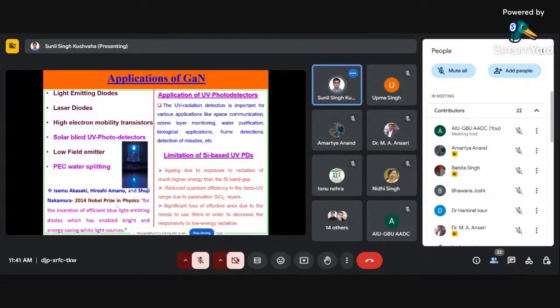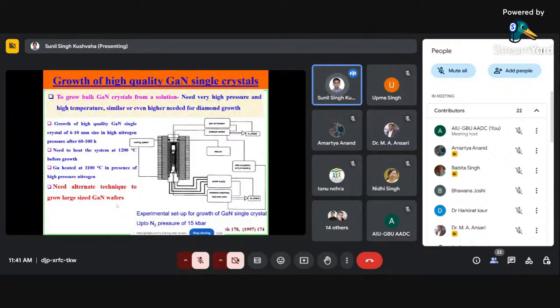As I previously showed, when we put in indium or aluminum nitride, accordingly it covers the whole spectrum. So this is the material, and of course it can be used for different purposes. Again, it depends how we are going to use it and whether we are able to grow it or not. One of the limitations, just to make you aware, is that it is not possible to get a gallium nitride wafer like a silicon wafer. Even when people started crystal growth of gallium nitride in 1997, they were only able to grow 6 to 10 mm size in 60 to 100 hours, even with 1200 degrees Celsius before the growth. Then people thought, okay, it is not possible. That's the gallium nitride technique. It took a lot of time before the commercialization of these LED devices due to the non-availability of large wafers like silicon.